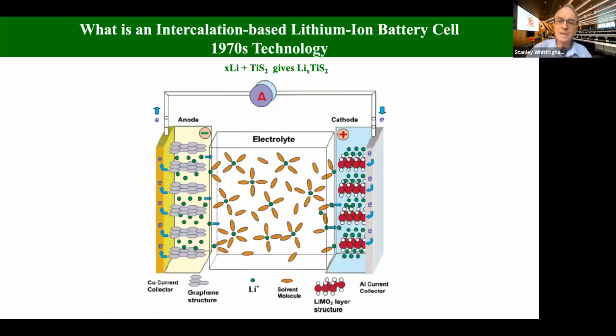Let me, just in case there's anybody in the audience who doesn't really know what a lithium-ion battery is, explain: every battery has an anode and a cathode, and in between an electrolyte. In a lithium-ion battery, you have lithium ions stored on one side when it's fully charged. When the battery discharges, it goes from an organic electrolyte into the cathode material. In the case of our initial Exxon work, this was pure lithium, and this was titanium disulfide. And in between here, there's a lithium salt, obviously an organic solvent, because aqueous solutions don't work there. So let's look at now a little bit of the history.